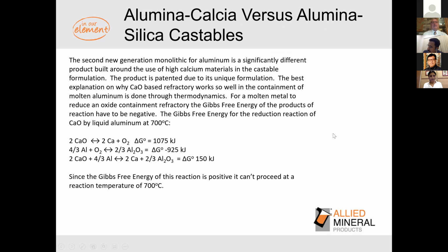Now, moving to the second product that's been developed for the 21st century: products that are based on high levels of calcium oxide. And why did we go from using Alumina-Silica based materials to materials that are Alumina-Calcia based? Well, the reason, as I started off the presentation showing, is how aluminum metal reduces silica. And the industry for the last 20 years has been making refractories with lower and lower levels of silica. Well, how about eliminating it totally and putting in a material that, from a Gibbs free energy standpoint, cannot be reduced at all.